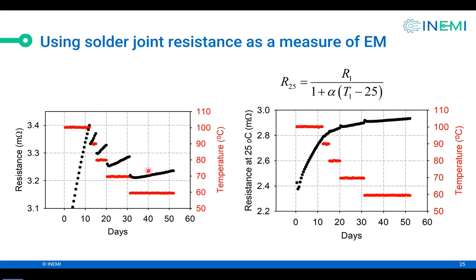So there are two things we want to examine here. One is the drop in resistance when we lower the temperature. The other one is why the resistance is dipping. Remember, I've shown you data earlier. We said the resistance dips because of grain structure coarsening. But here the grain structure is already coarse because we start at 100 degrees. So the specimen coarsens over the 10 days at 100 degrees. So this dip is not because of the structural coarsening. This is for a different reason. So what is that reason, right?